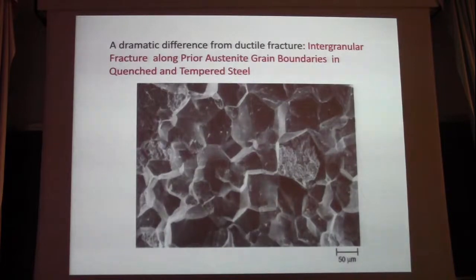But here is intergranular fracture. And it took me a while to get to this point, but look at the difference here. These surfaces outline the austenite that was formed by the austenitizing heat treatment. These are the boundaries between crystals of austenite. Fracture has proceeded along these, and very smooth, no evidence of microvoid formation, etc. Occasionally, a crack will go through a grain. The heat treaters that you use work very hard to produce tremendous structures within the austenite grains, but that's bypassed by these intergranular cracking mechanisms.